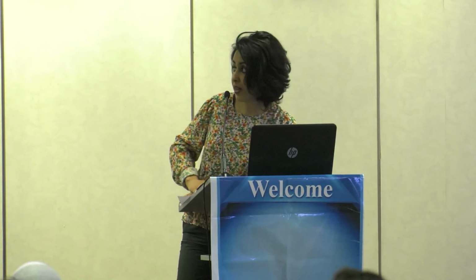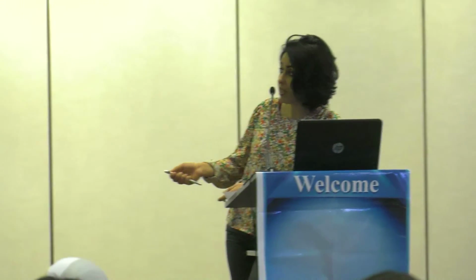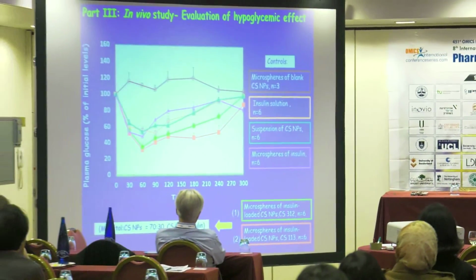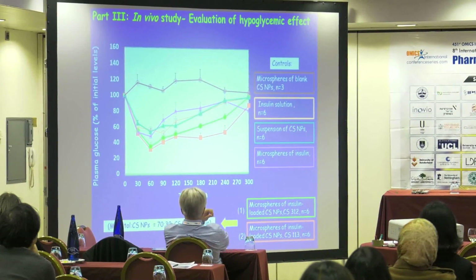Here we have the results after the in vivo study, showing the hypoglycemic profile. We can see that the control formulations did not induce a significant effect, while the powder formulations induced a significantly higher hypoglycemic effect, which was prolonged over 6 hours.